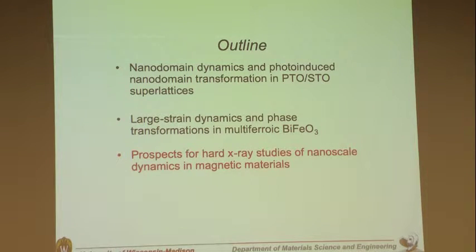What we thought might be interesting is this: you might remember at the very beginning, I showed you a map of the ferroelectric domain population as a function of position. Everybody remember that? And then I said, let's make that time resolved. And we did. The reason we could do that is that we have enough intensity that you can afford to divide the APS by whatever the repetition rate of the laser is with respect to the pulse rate. We have a 6 megahertz rep rate for the APS and a 1 kilohertz rep rate for the laser. All of your signal is divided by a factor of 6,000, right?